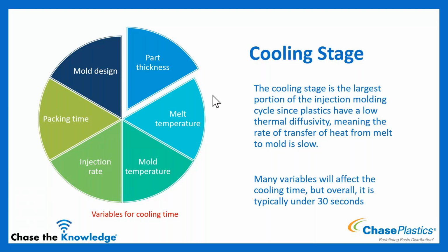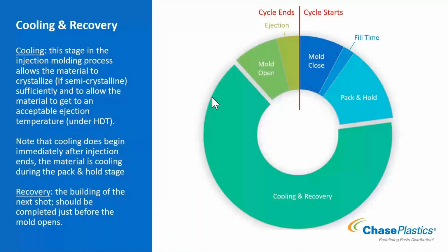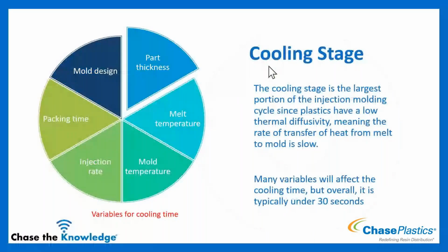Now, we can notice from this pie chart as well that cooling is the largest portion of the injection molding cycle. And this is because polymers typically have low thermal diffusivity, meaning the rate of heat transfer from the polymer to the mold is slow. And it slows down over time as we're solidifying and as an air gap starts to form as we shrink away from the cavity surface.